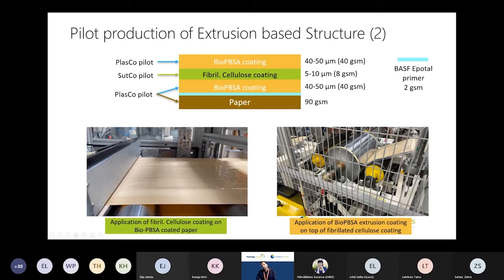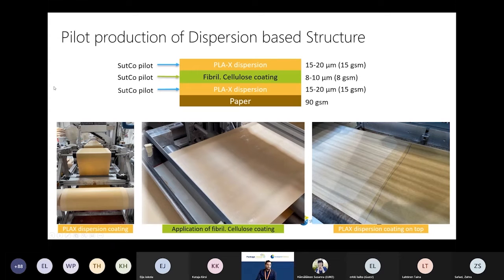And this structure was again produced in a similar manner: on Plasco, extrusion coating of paper with bio-PBSA; on the SUTCO pilot, fibrillated cellulose coating; and then again on Plasco, bio-PBSA coating. And these were the GSMs of these different layers. You can see some pictures of this production process here. And then the dispersion-based structure was actually produced on the SUTCO pilot line, because there we did not have to use extrusion coating technology at all.